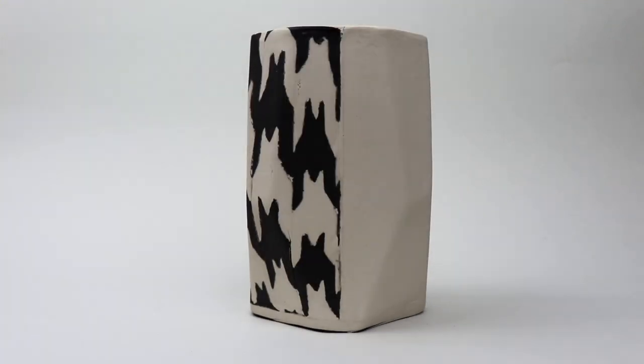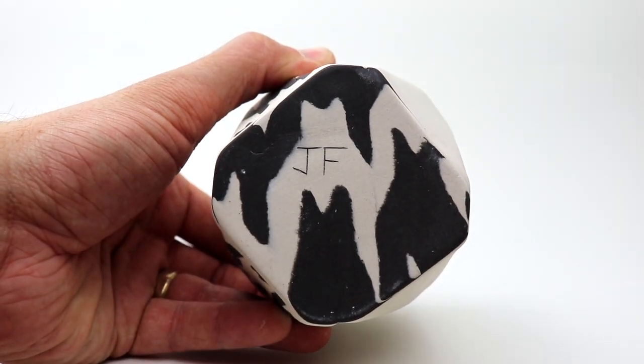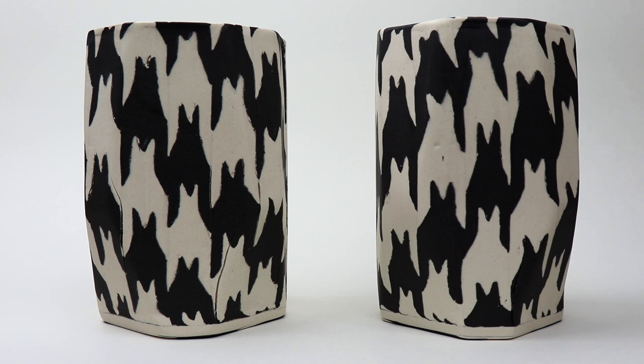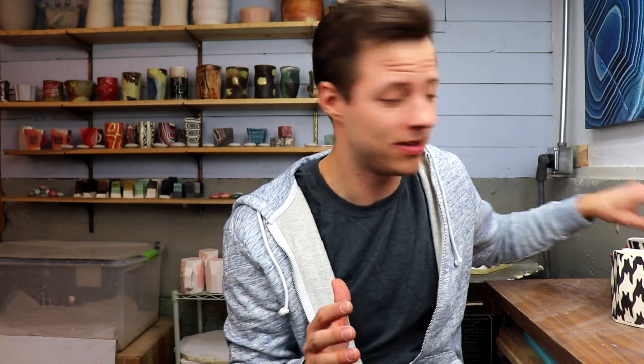You can see a lot of cracks in this work. The more you work the clay, the drier it gets, and when you're attaching all these pieces together, you're kind of asking for this to happen — especially when you bend it the way that I'm bending it. After you make a big block of nerikomi, it's good practice to wrap it in a damp rag and a bag and leave it there for a week — some people say a month — so all the clay can soften up to the same consistency. But sometimes you just can't avoid this; part of the process is risking it happening. Nonetheless, I'm really happy with how these pieces turned out. Imagine if all those houndstooth pieces had different colored designs within them — I feel like the possibilities are endless.